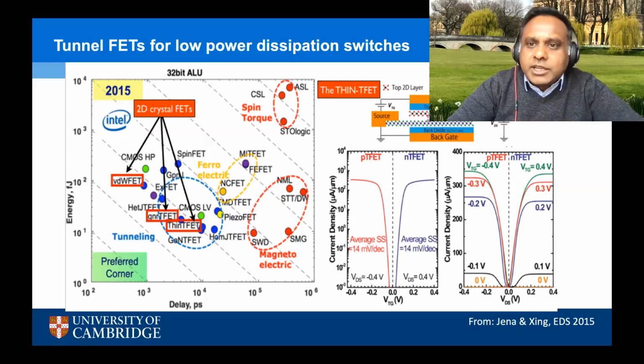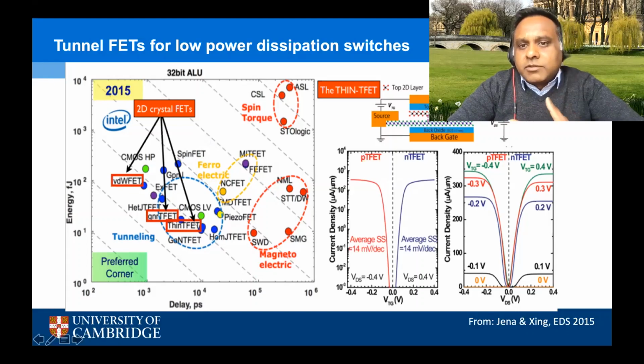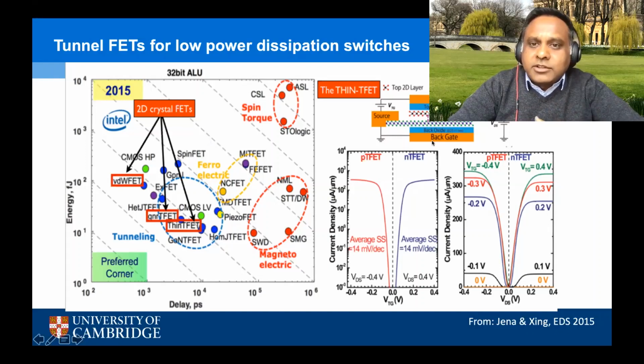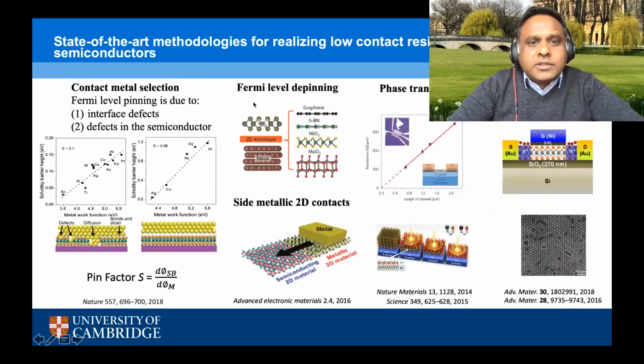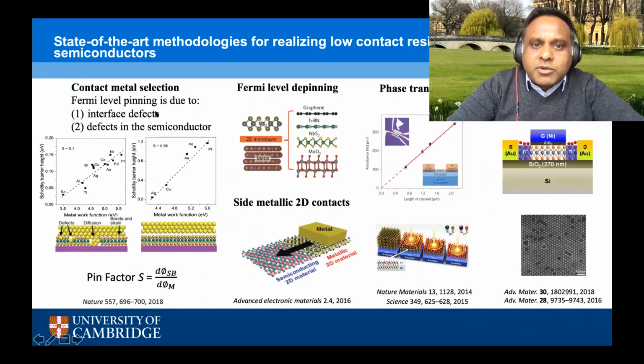It's not a very sexy problem, if you will, but the problem of contacts really has become very important in 2D semiconductors, because we've not been able to reliably make both N-type and P-type contacts on different types of 2D semiconductors. So for example, MoS2 always gives us N-type characteristics, but in principle, there's no reason why MoS2 should be N-type. It should be an intrinsic semiconductor, but the FET characteristics are dictated by Fermi level pinning at the contacts. So let me just summarize the work so far that's been done on contacts.